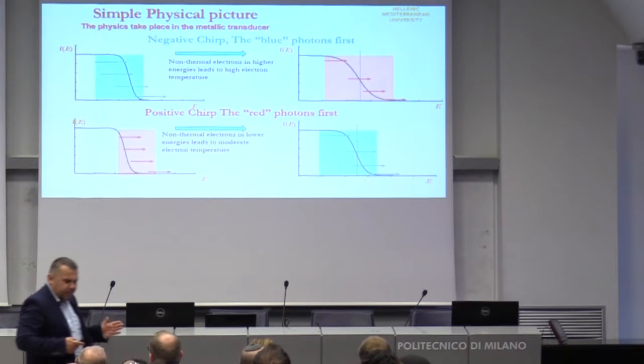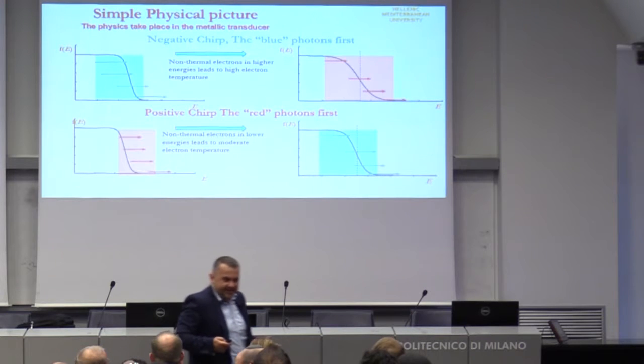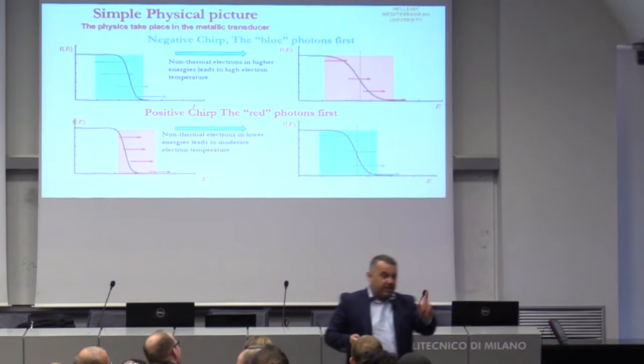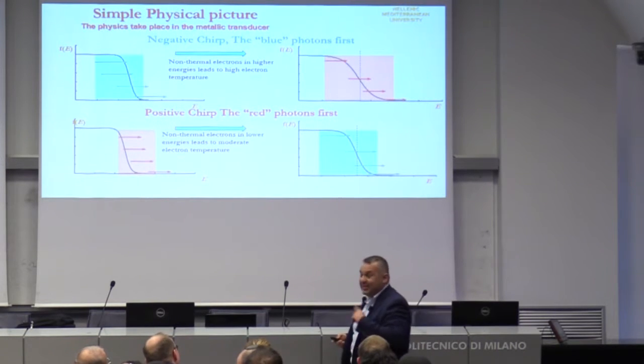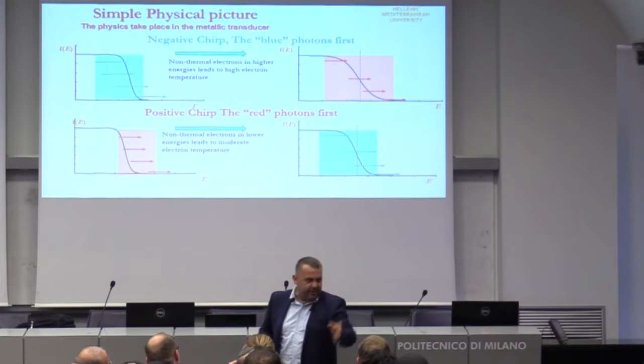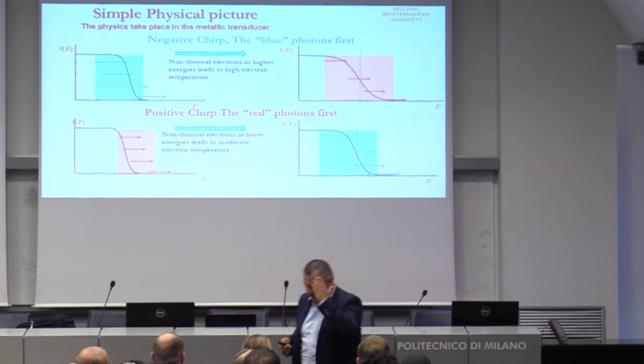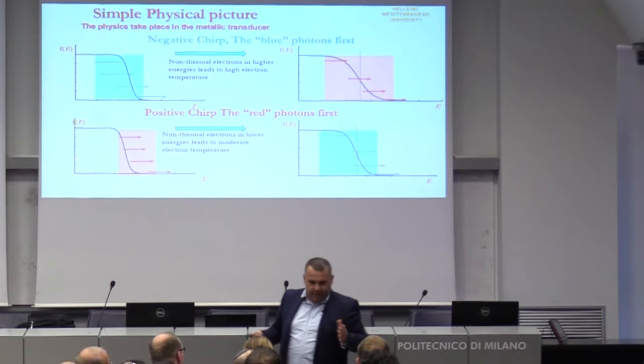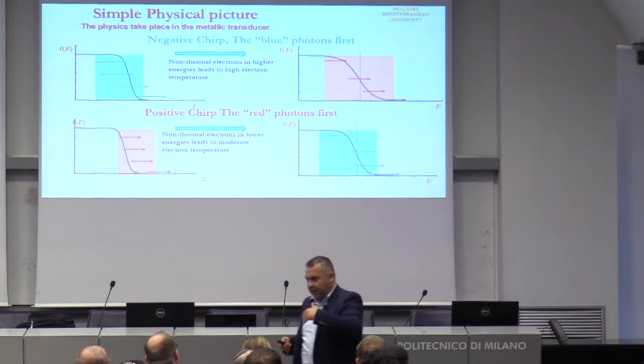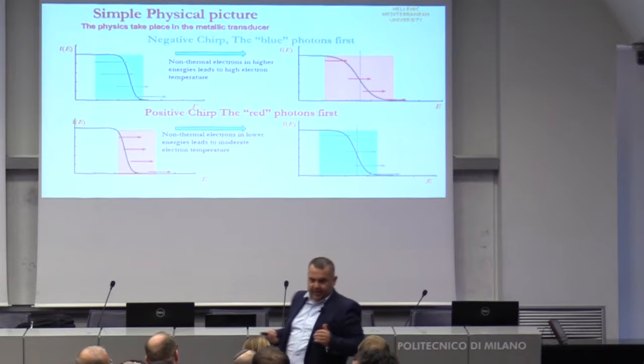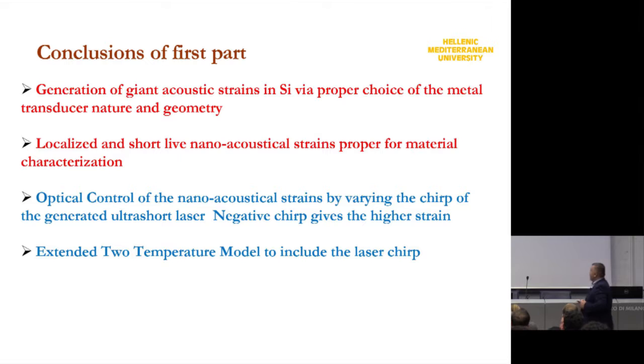So Fourier limited pulses are not always the best pulse. We need a bit of chirp sometimes. But unfortunately for this process we need negative chirp, because positive we can do very easily. We put a plate, we pass through the laser, but negative you need specially designed apparatus like multi-layer mirrors and things like that in order to do the negative chirp. Now, these are the conclusions of my first part.